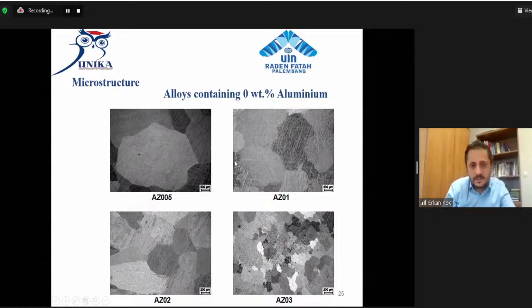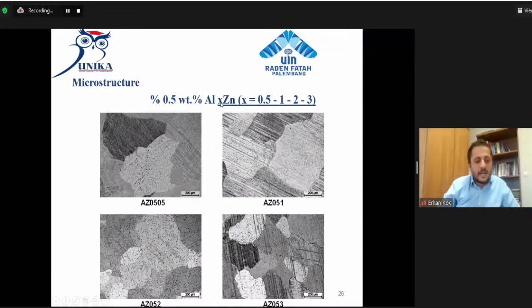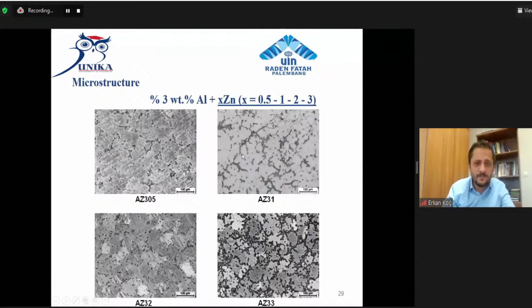It's a big grain, and when you add zinc, the grain is refined. If you add 0.5 weight percent aluminum, the aluminum addition dissolves as a solid solution in the microstructure, and the grain size decreased again with the increase in the amount of zinc. You can see the microstructure clearly, and it's interesting in the 3 weight percent aluminum. If you add aluminum and zinc at 3%, you can easily see intermetallic particles here. It affects corrosion, of course.